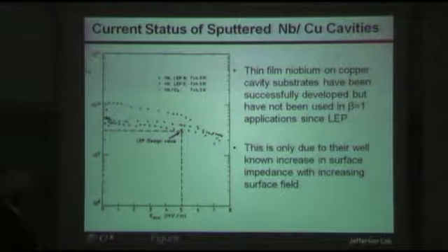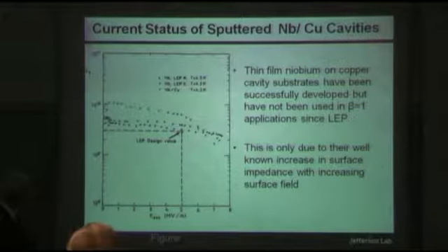And I'm not going to talk much about conventional sputtering, even though I'm comparing that to energetic condensation. Everyone is familiar with the type of severe Q droop, the non-quadratic losses that you get within niobium films. The CERN group over many years has done a fantastic job of analyzing and doing experimental work on those issues. So I won't go into those. But this, I would also say, is probably the only reason I can think of that has kept niobium copper cavities, thin film niobium, used in actual applications for beta equal 1 applications anyway, since LEP. I think there's no reason for it other than that.